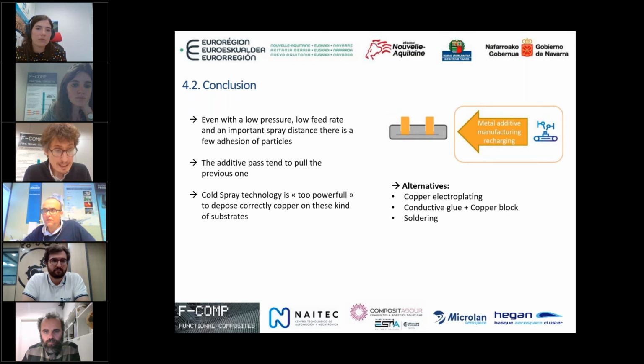This put us in the situation of looking for alternatives, like copper electroplating, using conductive adhesive, or even soldering. This is because cold spray is good for certain applications. In metals, it is perfect, and Cometa and COMPOSITADOUR have worked on it over the years. But for these very smooth materials, it is too powerful to achieve correct deposition. So, it's a lesson learned from this project.